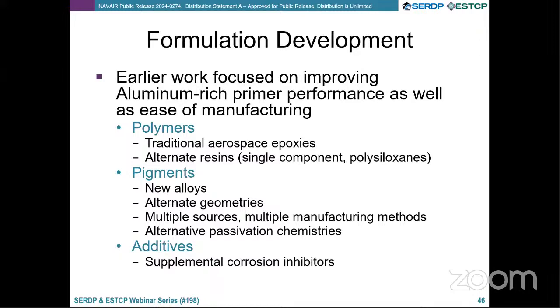And then finally, because we had a need to reduce pigment loading, as obviously the more pigment available in the film, the better it has a chance of contacting and then performing in the electrochemical reactions. But that might have negative effects on some of the other properties of the coating, like flexibility, adhesion, as you had learned in Eric's talk. And so we were able to reduce pigment loading by incorporating other classes of corrosion inhibitors in minor amounts within the film. And through studying what is the right way to move inhibitors to different surfaces, we learned that there's specific classes of inhibitors that are compatible with the aluminum-rich primer, and plenty that aren't, unfortunately.